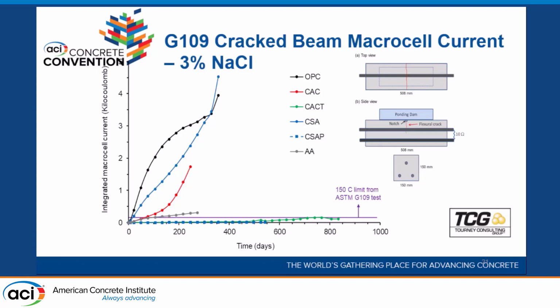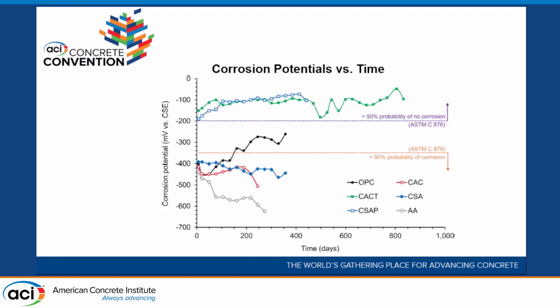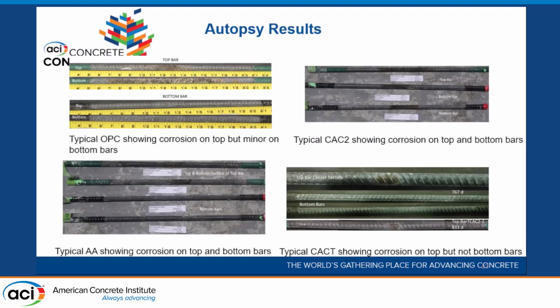CACT, which was calcium aluminate with a belite in it, did extremely well, as did a couple of the CSAs, where one of the CSAs and the polymer one were down there. Other ones eventually went into corrosion at one time. The CAC, which started off pretty low, just took off when it went through its phase transition. Once again, these things aren't seen in any environment other than chloride, the normal environments they would be expected to see. Looking at corrosion potentials in time, they very much show the same effects, with the control samples starting to passivate a little bit. But even though I'm an electrochemist, I do like to look at my bars when I'm done testing, because if people tell me I didn't see any corrosion, well, that particular test method only is measuring the macrocell.